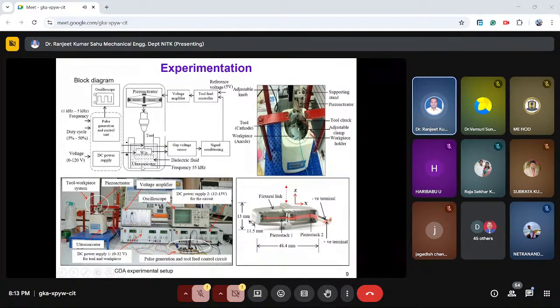This ultrasonicator can also aid in the efficient removal of debris from the spark gap region and avoid accumulation of debris in the spark gap. This will result in stable spark discharges or corona discharges and increased machining efficiency. In this setup, a piezo actuator was used. This is a piezo actuator figure. The piezo actuator is used to feed the tool towards the workpiece, to maintain a constant gap between the electrodes during the machining process.